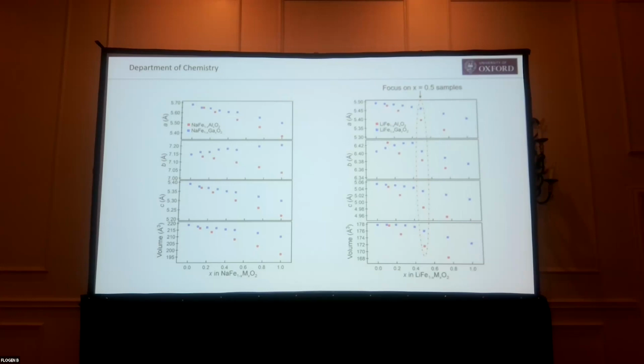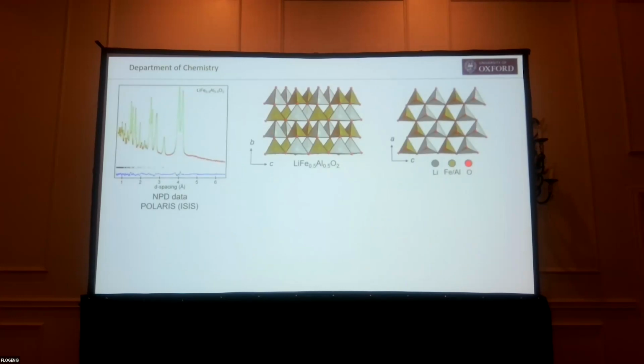So what we want to do first of all is check the structure is correct. And these are just X-ray data. We can't find the lithium with X-ray data, so what we can do is take neutron diffraction data. So this is neutron diffraction data from Polaris. This is one of the 5 data banks from the normal data here. This is just illustrative to show that, yeah, this material where we've got 50% substitution of iron by aluminium gives us a nice structure.